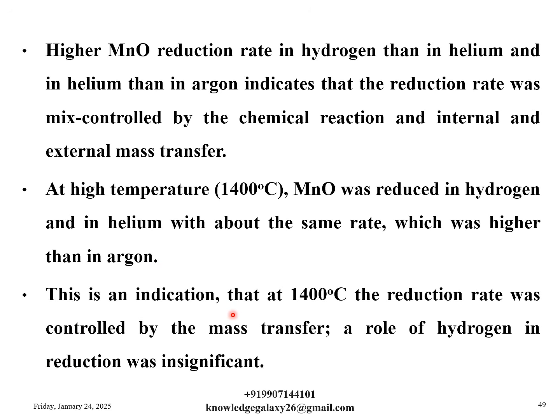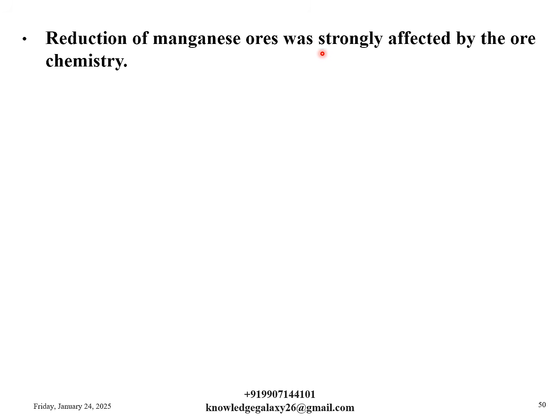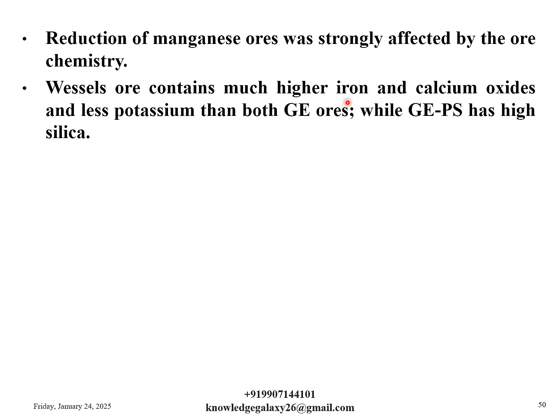This is an indication that at 1400 degrees Celsius, the reduction rate was controlled by the mass transfer, a role of hydrogen in reduction was insignificant. Reduction of manganese ores was strongly affected by the ore chemistry. Vessels ore contains much higher iron and calcium oxides and less potassium than both GE ores. GE is Groote Eylandt, that is from Australian ores, while GEPS has high silica content.